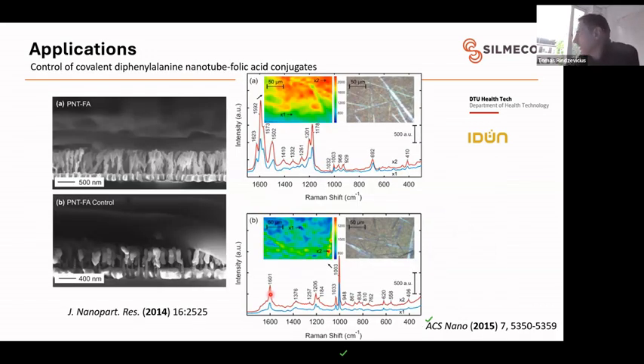And another example I have here is a specific science case where one group had been working with these nanotube folic acid conjugates for some cancer detection application. But they wanted to know whether their conjugation procedure or the washing procedure can get rid of the free folic acid. And this is where SERS turned out to be useful because here in A, you see this tube lying on our pillars, and we can see basically a spectrum of folic acid. And then the question was, is the spectrum coming from the folic acid on the surface of this nanotube or from free folic acid that is simply in solution, and they were not able to wash it away in the chemistry step.